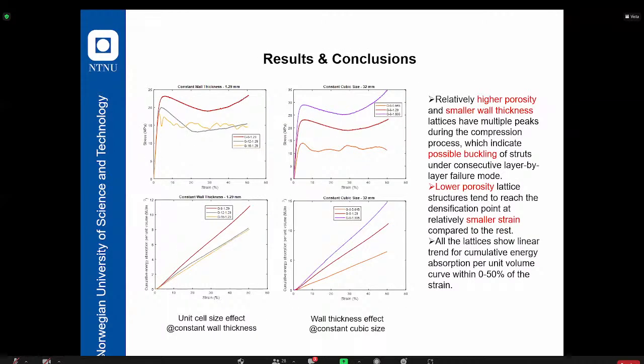And these are the results for the other 2 categories. As we can see from these curves, the majority of the stress strain curves have a really smooth trend, but some of them have multiple peaks during the compression process, which indicates the possible buckling of the struts under a layer by layer failure mode.